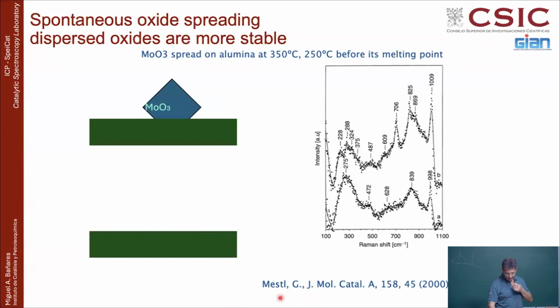This is from a review from Gerhard Mestl, but it refers to a very old paper from the 70s or 80s, where you are looking at the Raman band of molybdena, over there, before and after calcination. What happens is that this bulk crystalline molybdena spreads into dispersed molybdenum oxide. And Raman can see that, even with the very old Raman system, very noisy. The nice thing is that molybdena was spreading on alumina at 350. That is very interesting because the melting temperature of molybdena is about 600 degrees C. So why should it spread so soon?